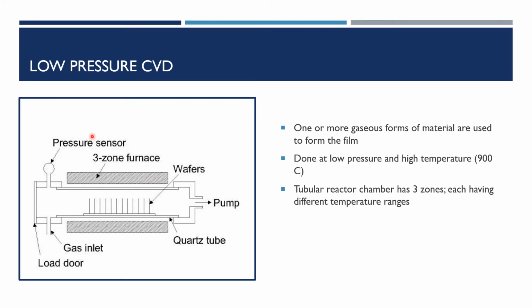So this is used to deposit different materials on the wafers at different temperatures. For example, the deposition of tungsten on the wafers is done at 400 degrees Celsius, whereas the deposition of silicon oxynitride is done at 800 degrees Celsius. So those wafers which need silicon oxynitride can be kept at zone 3, and those wafers which need tungsten can be kept at zone 1 where the temperature is low. So that is how the three-zone furnace is used. It heats the quartz tube.